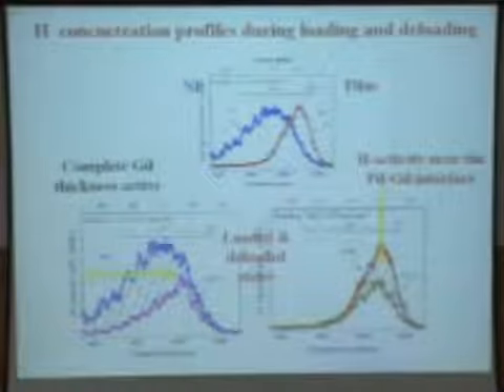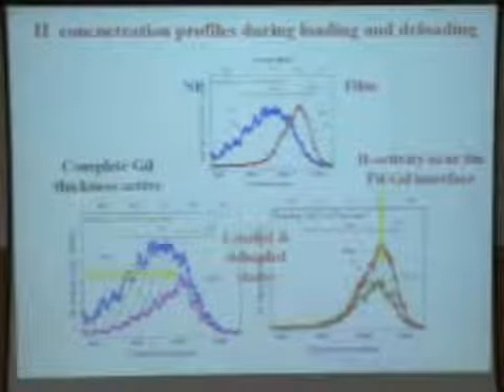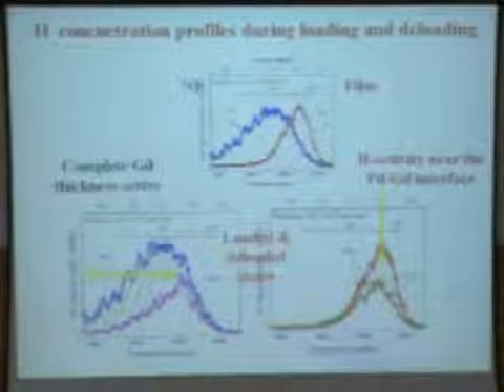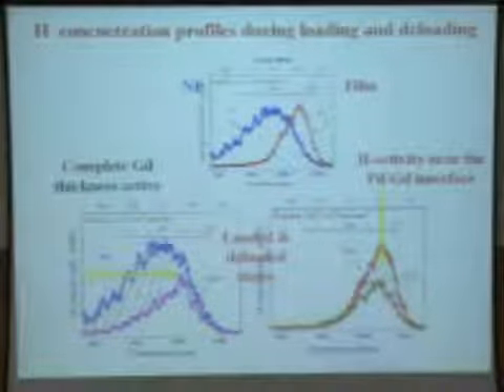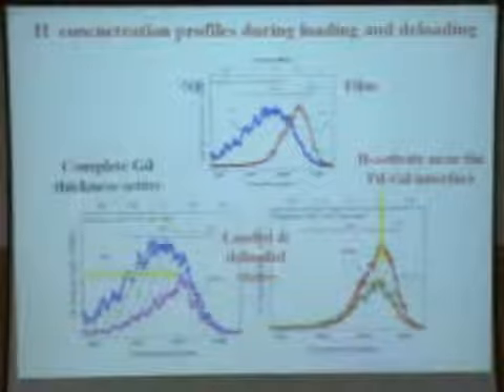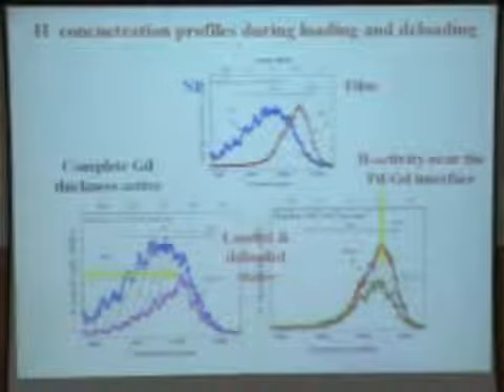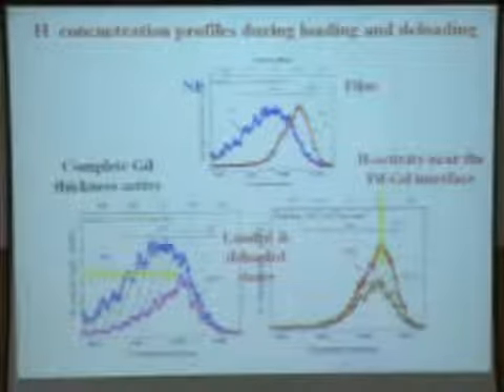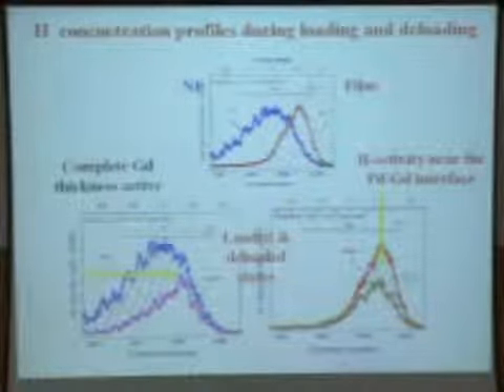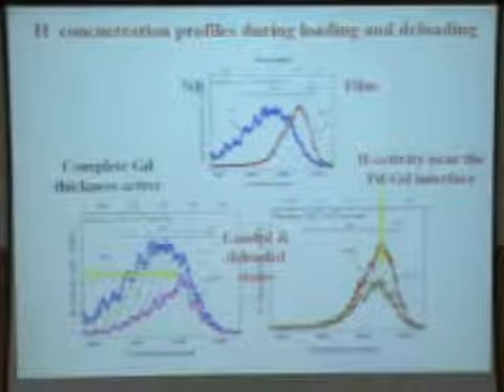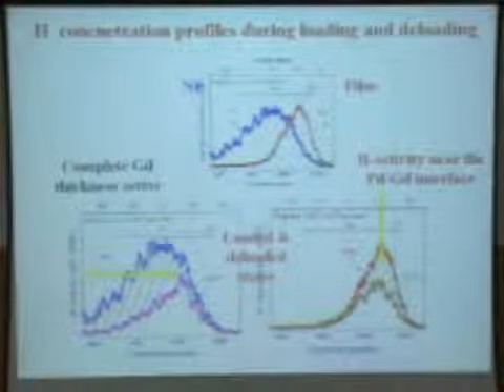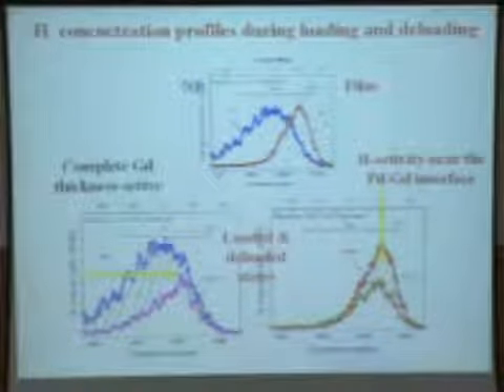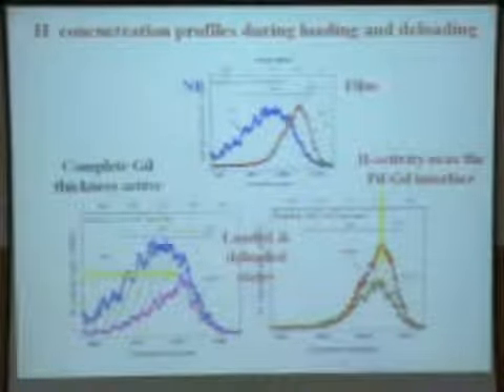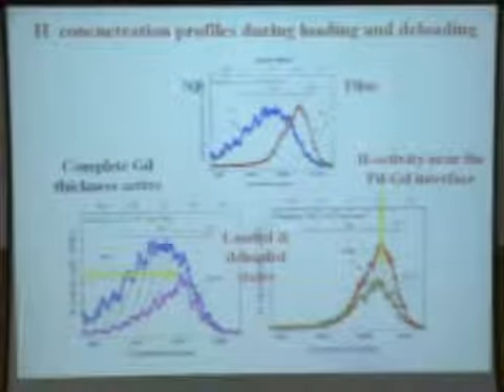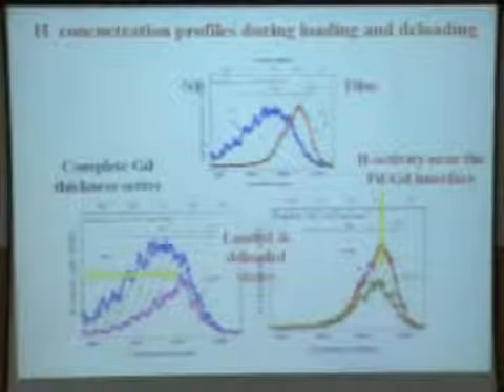Because of the incoming vapors, when they come and get deposited, they collide with the argon inert gas atoms, they lose their energy, and when they reach the substrate, they cannot move on the substrate with high kinetic energy, so that results in small crystallite size. The problem in this technique is that the size distribution is very broad. You have particles of all sizes present there. So we can only compare a thin film with a nanocrystalline or a polycrystalline layer with a crystallite size. Average crystallite size is something like 20 or 18 nanometer, but we cannot change the crystallite size.